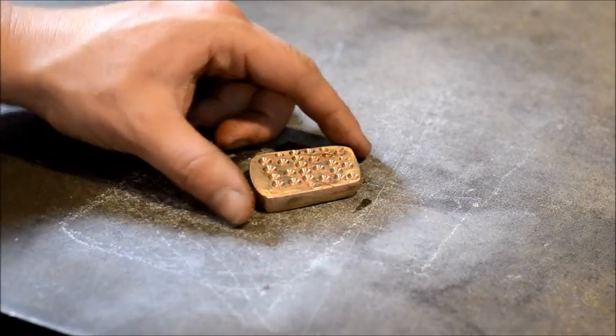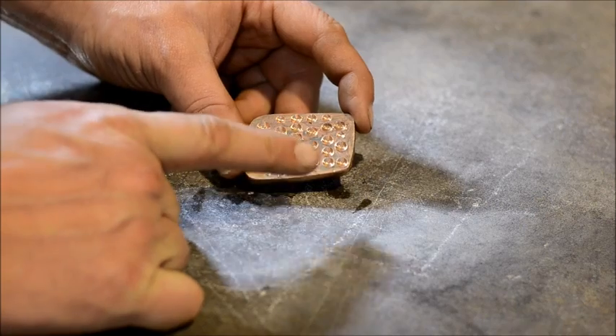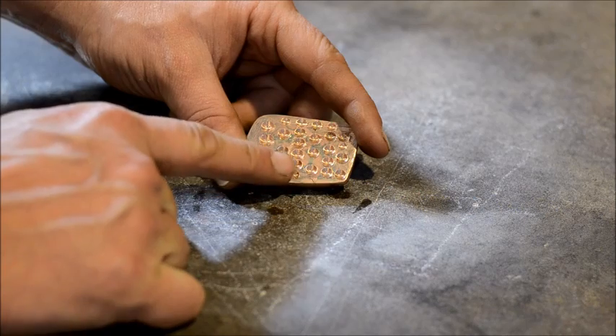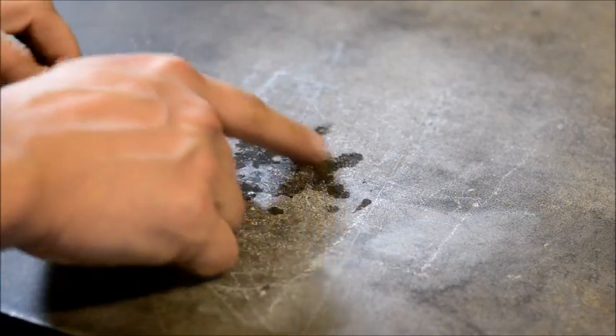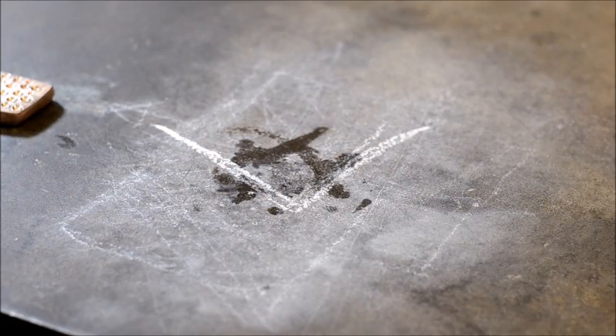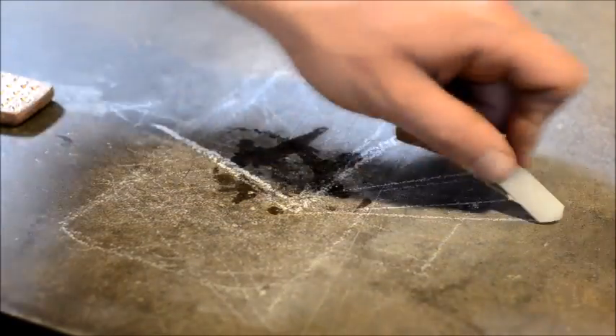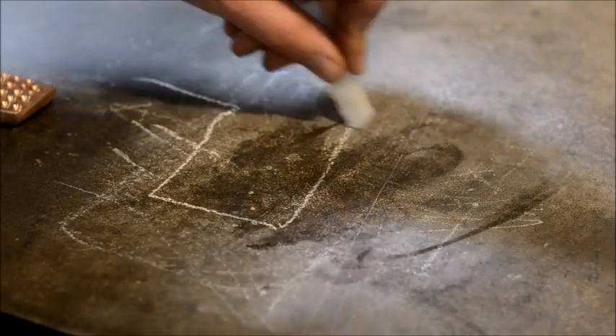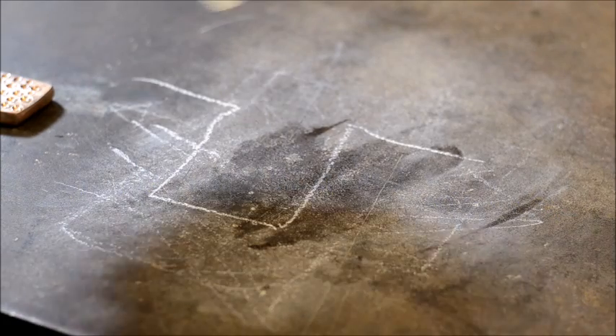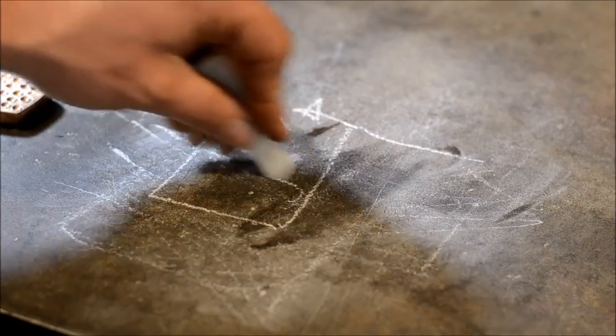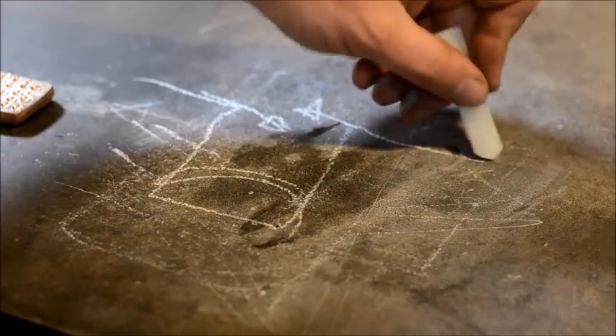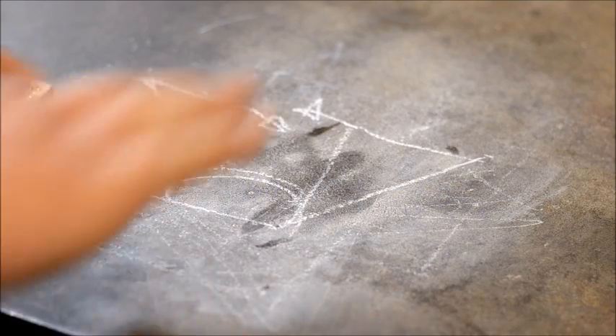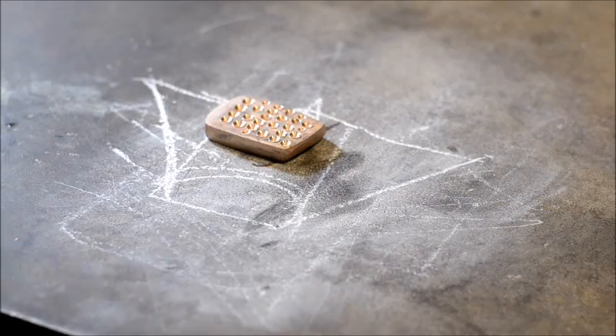One thing to take and notate: these are not drilled holes. A reason for that being is a drilled hole, the hole would collapse in on itself and close up, and then you just have a bunch of little tiny cold shuts. These are a bevel. They look like that. That is important. So this way when you forge this down, you can askew those layers out to where you can see them. If you just drill a straight hole into a piece, as soon as you start forging on this, these walls are going to collapse inwards and create a pocket. And that's just going to be an inclusion later on. We don't want that. So by drilling at a diagonal, having a nice chamfered hole like this, what we are doing is we're actually pushing the material away and exposing the grain that we're wanting to get at.